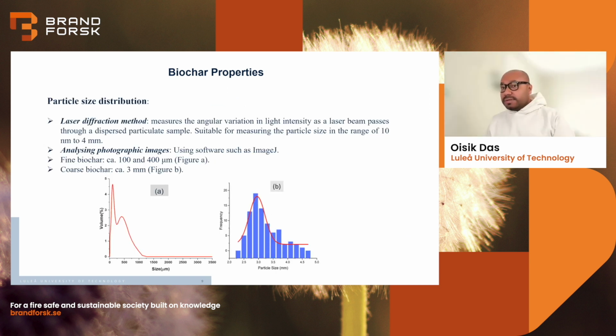Then for the particle size distribution, we have used two different methods. The first one is the laser diffraction method. It measures the angular variation in light intensity as a laser beam passes through dispersed biochar samples. And we have also used a software called ImageJ to analyze photographic images to find the particle size distribution. From the laser diffraction method, we used the fine biochar, and we found, in graph A, that the particle size ranges from 100 micron to 400 micron. So the two dominant particle sizes are 100 micron and 400 micron. And for the coarse biochar, which was made from the olive pit, the particle size was estimated using ImageJ software, and it's about 3 millimeter in size, as given in figure B.